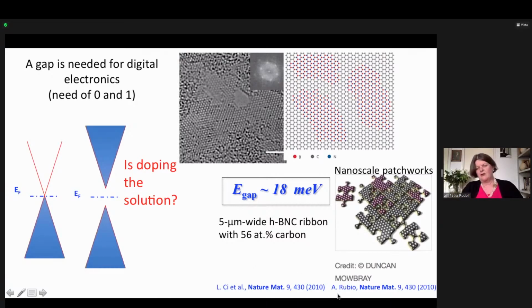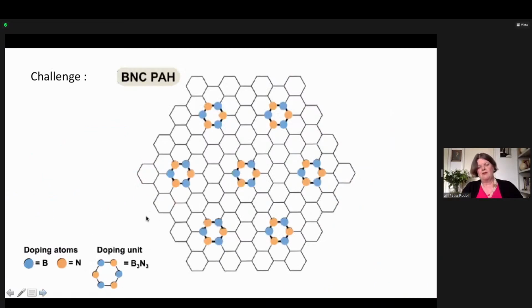And Angel Rubio published a very nice comment in Nature Materials, where he explains that even this situation can be useful if the domains are small enough. We are working on this. Right now we are producing domains which are of the order of a few nanometers, which is still too big. We are trying to get single hexagons of boron and nitrogen, and we hope to reach that soon. We are not there yet, but this is a big challenge that lots of people are working on.